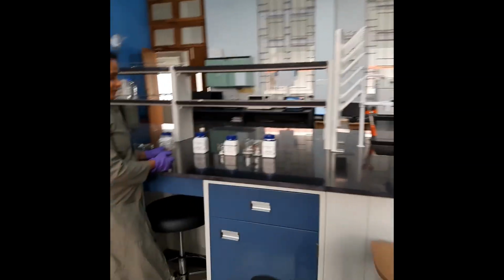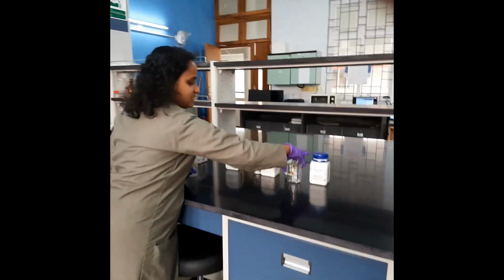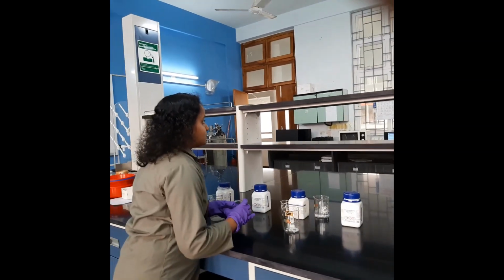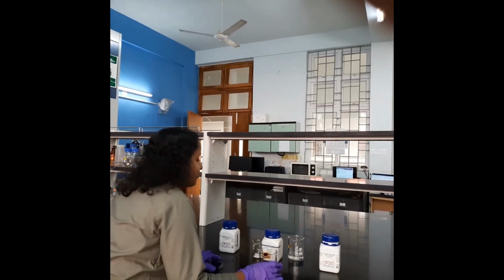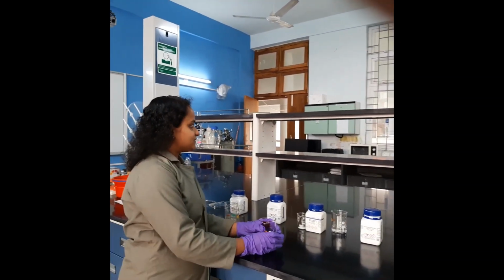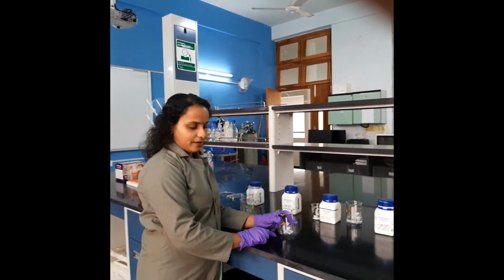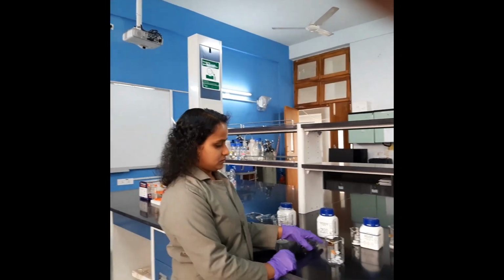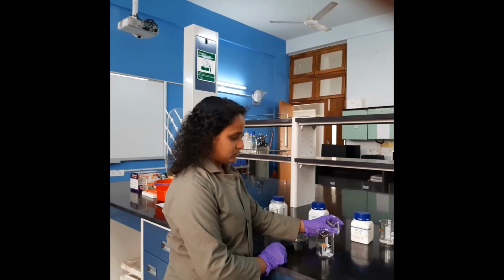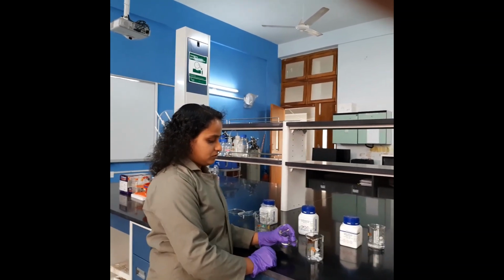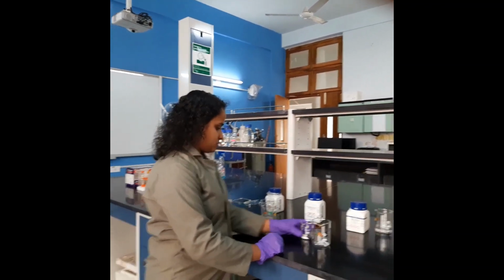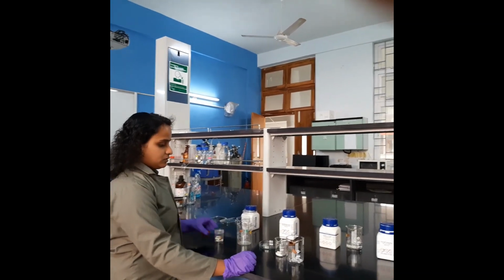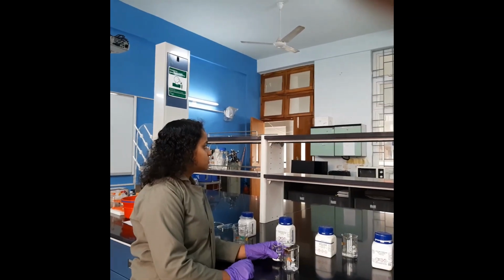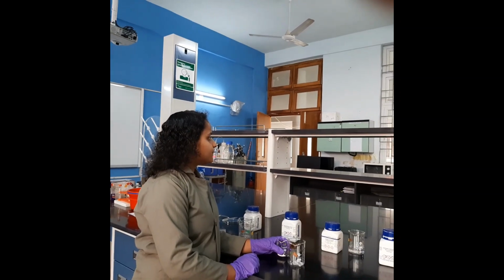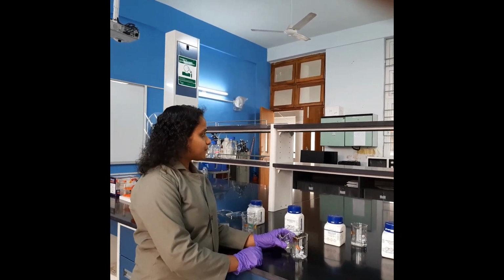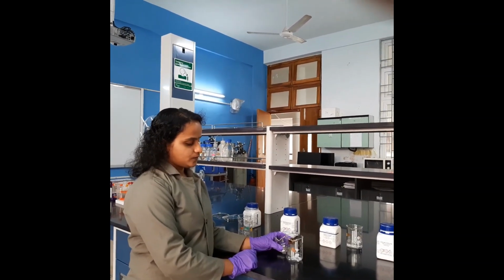For preparing the base solution, we have taken 120 millimole sodium hydroxide, that is 4.79 gram. We need a large excess of sodium hydroxide because the total metal salt we have taken is 53 millimole, but here you can see 120 millimole of sodium hydroxide, which is a hydrolyzing agent. So it basically needs an excess of base. The pH will be around 8.5 at the end, so we can see that.